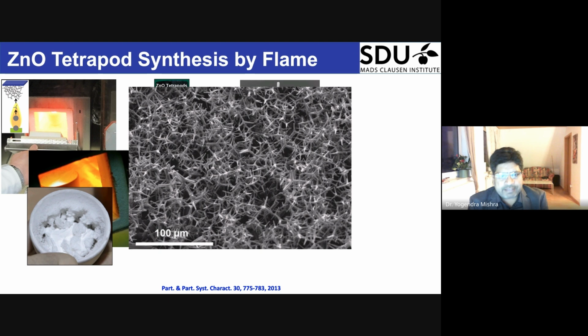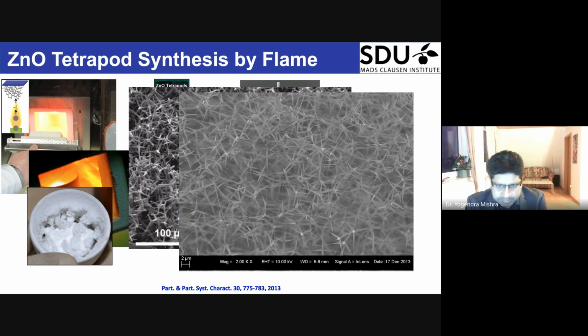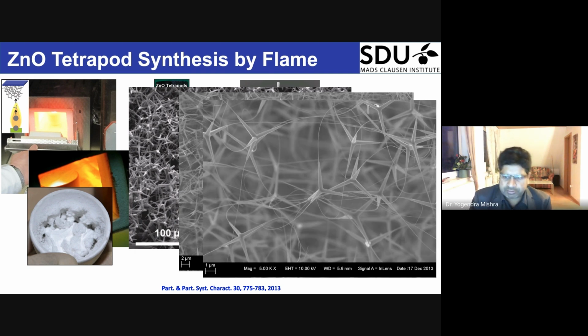And here you see how these tetrapods form by stepping on each other with a certain degree of porosity, which is self-controlled, more or less. It is a loose powder. And by changing the process, we do have the possibility to change the aspect ratio of these tetrapods, because that is the most important thing. We can go from large structures to really micro scale diameters. We can even change the length of the tetrapods in a very nice way to high aspect ratio structures.